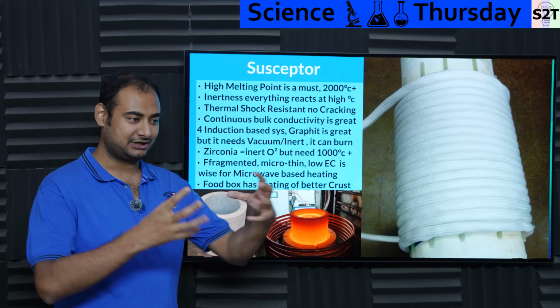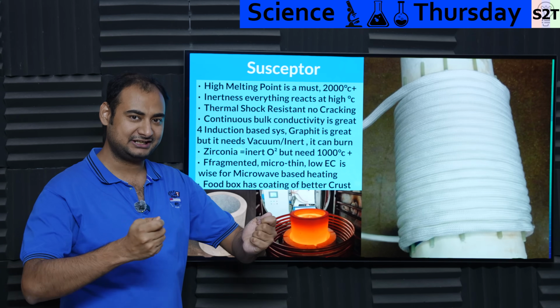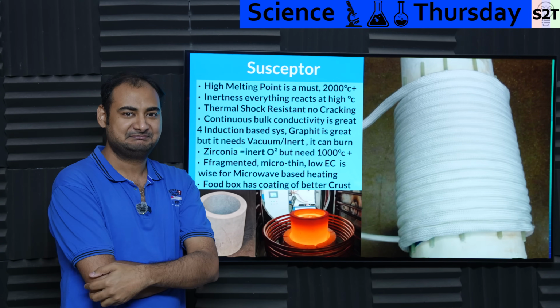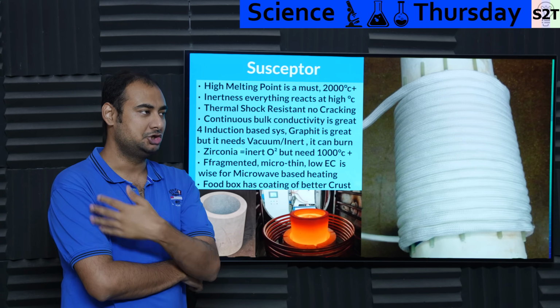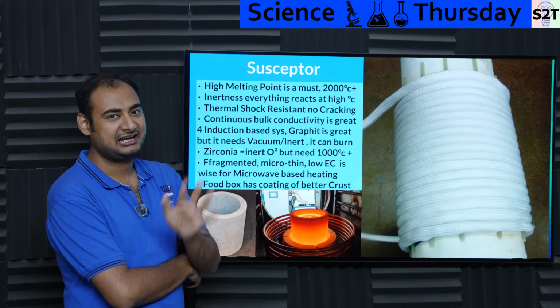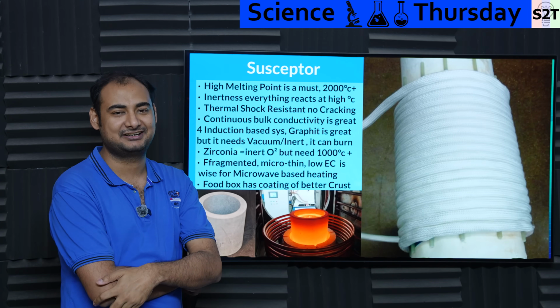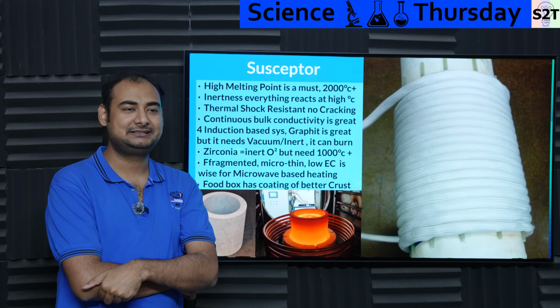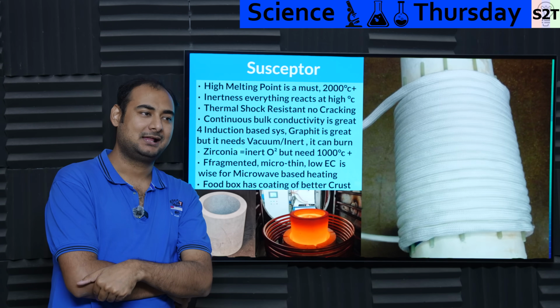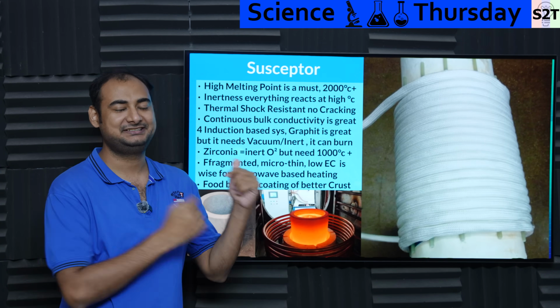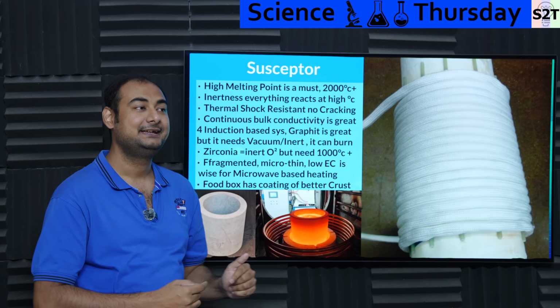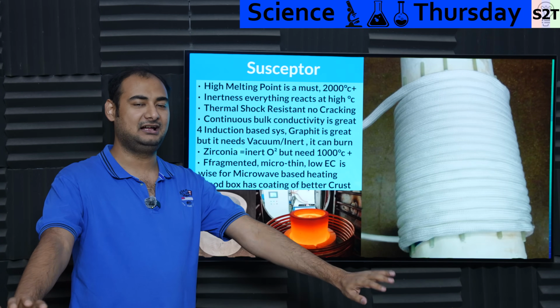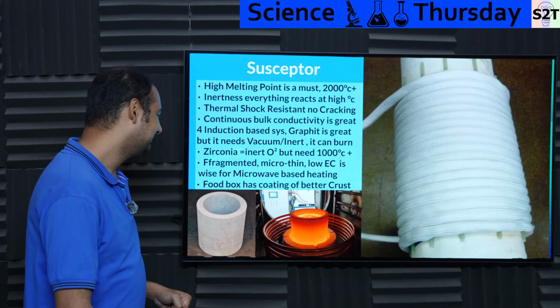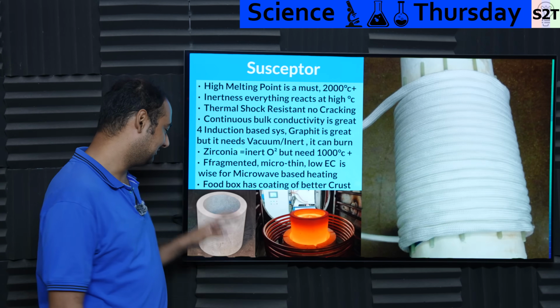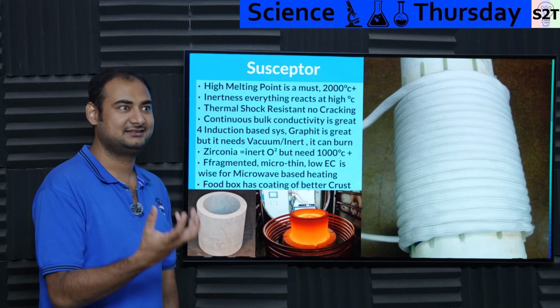As in, if you put zirconia in and turn on the inductors, nothing will happen. Nothing. It's like, nope, I'm not magnetically reactive. So how the heck do we turn it on? Well, you have to preheat it to 1000 degrees Celsius. That's its requirement. Thou shall heat it up to 1000 degrees Celsius. Then it's like, I'm going to react with the magnetic field. It's up to you to figure out how to have a zirconia crucible and then preheat it.